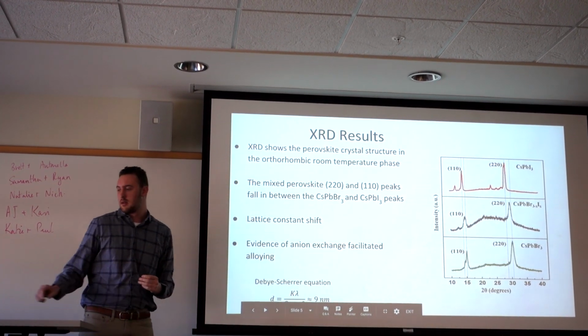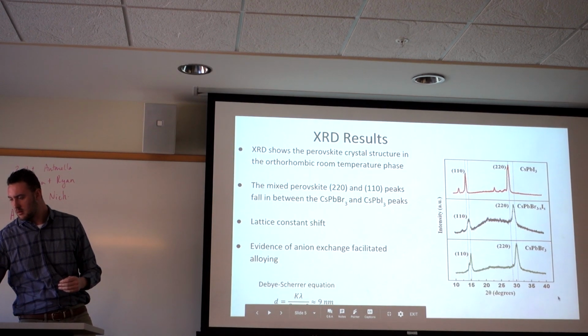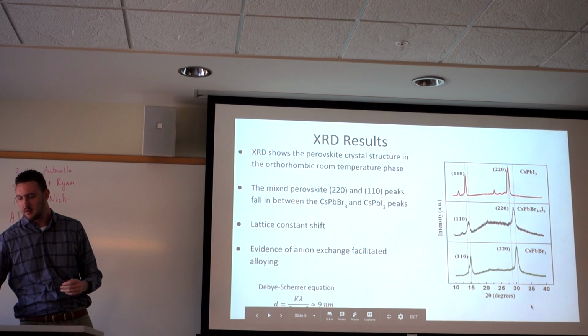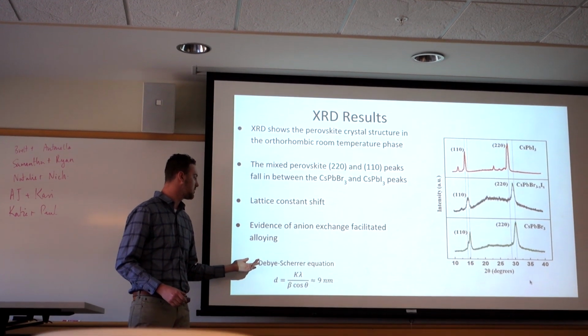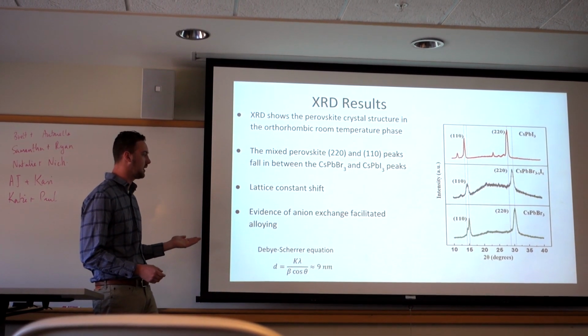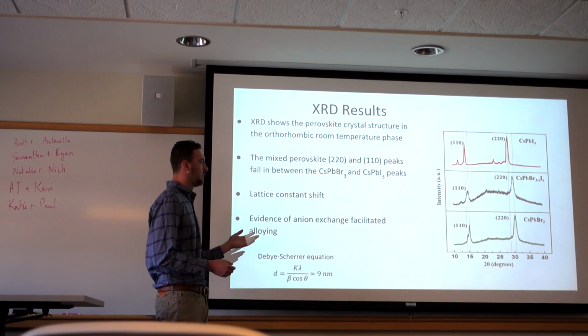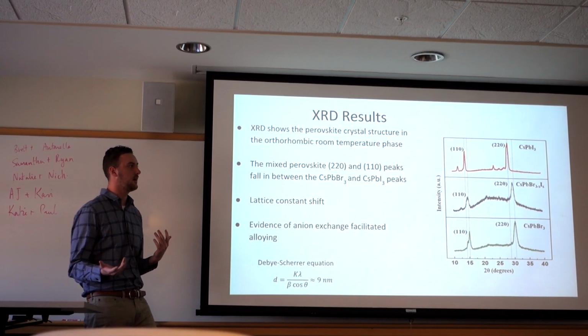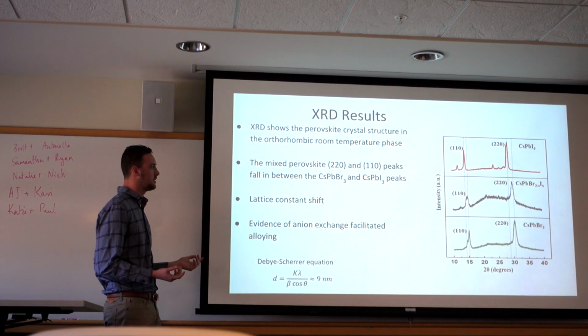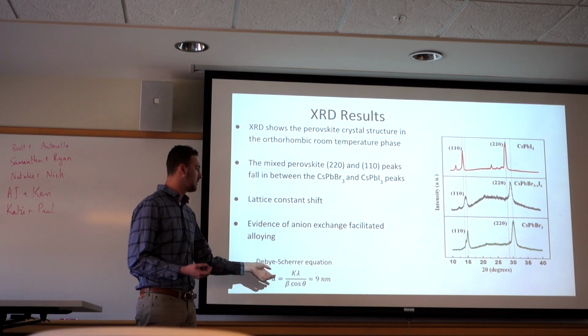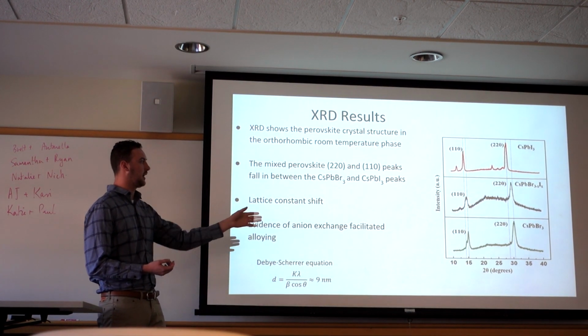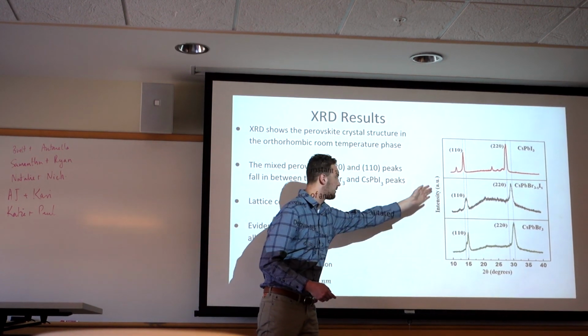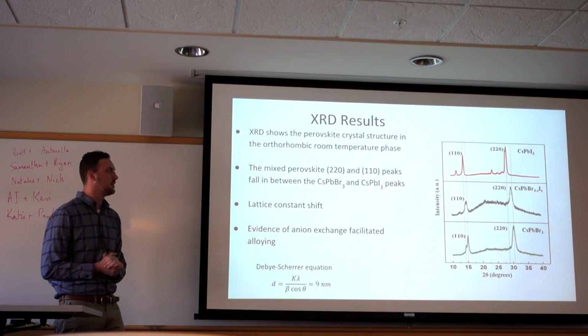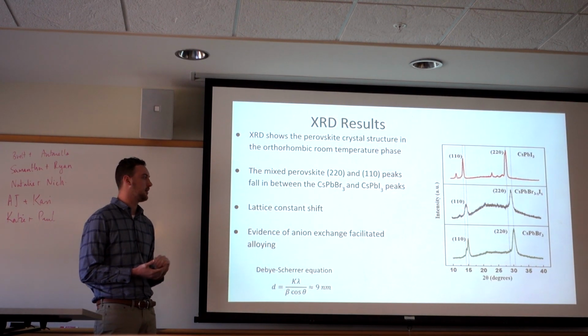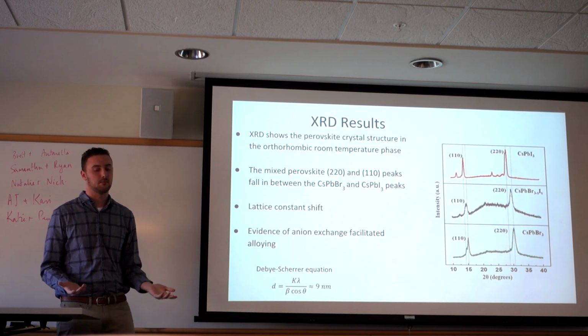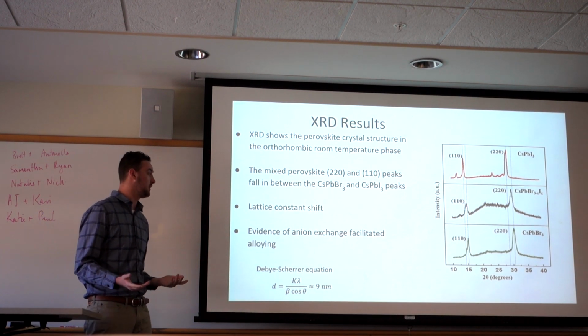And then using the Scherrer equation, we use the form factor K, the wavelength of our X-ray source, which was 1.54 angstroms, beta, which is the full width at half max of our peaks, and theta is the Bragg angle, so where these peaks occur. And we determine the size of our quantum dots to be about 9 nanometers, which is very good for a quantum dot, which is supposed to be between 5 and 10 nanometers.